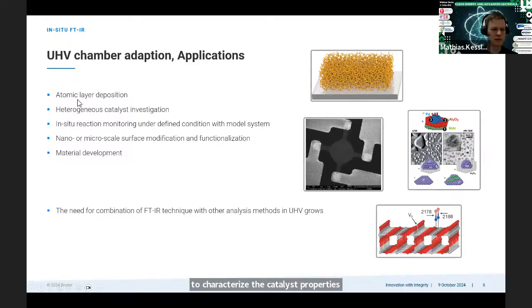We can also use it to measure and understand atomic layer deposition reactions. We do in situ measurements of catalyst model systems. We have the possibility to measure microstructured surfaces, and this is all very important for material development or catalyst design. And often, or almost always, these UHV chambers are designed in a way that we can apply different spectroscopic measurements. So then it's mostly not only FTIR, but also, for example, X-ray spectroscopy techniques in addition.